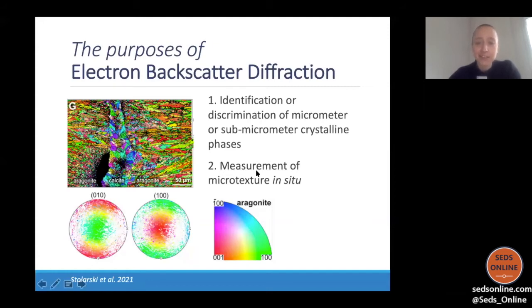And the second application is the measurement of the so-called microtexture in situ, and these are these colors that you see on this map. The colors correspond to the orientations of crystallographic axes. And this can also be expressed using the so-called pole figures, which you see here. These are two examples for the aragonite phase. So this is the legend. And the legend shows you how to